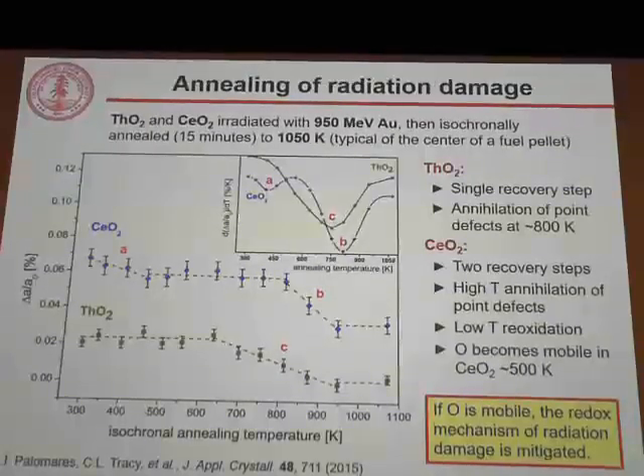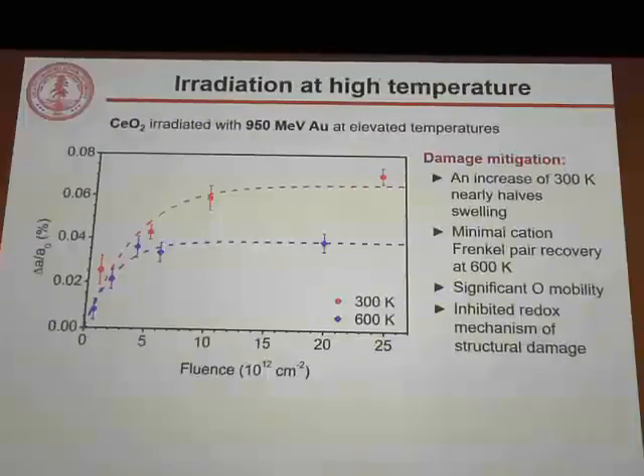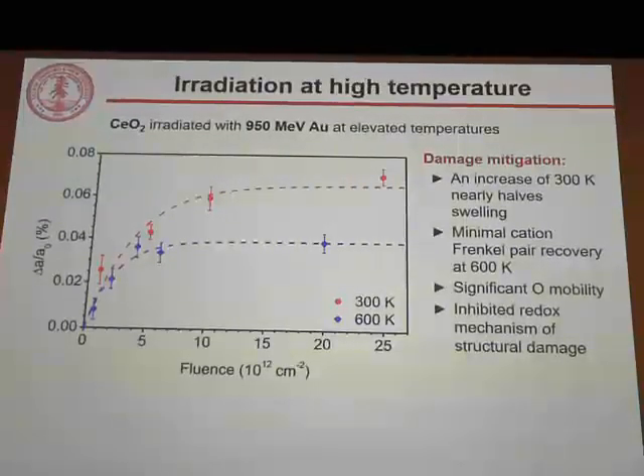of this material. So next step we looked at was what happens if we irradiate this material at high temperature. So not annealing it later on, but irradiating it while it's at temperature like would happen in a reactor. And we see that if we increase the temperature at which we're irradiating this material from in red 300 Kelvin to in blue 600 Kelvin, so a fairly small increase in temperature, well below what is encountered, for example, at the center line of a fuel pellet, the swelling that is induced is nearly halved.